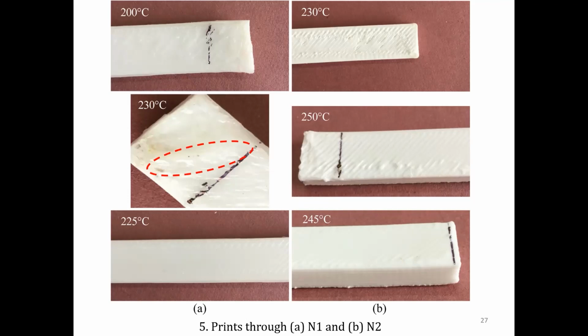There are two ways to increase the flow of the material. One, you increase the temperature of nozzle 2. We set it at 250. Then the higher nozzle temperature made the material flow out continuously, but with lump deposition at several locations. So again, we need to lower by 5 degrees, and these are all trial and error methods which you can always do. And also, based on this, we need to modify the extrusion multiplier.